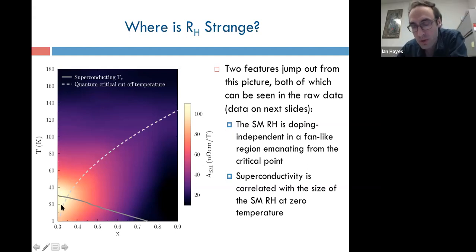That could well be true. It's a little difficult for me to answer with the high fields data because of the very limited field range available at optimal doping. I'll show you the raw data in just a little bit. When I do the fits and try to estimate how large the strange metal RH actually is, it does top out at around 10 to 15 Kelvin or something. Okay. So that is potentially consistent with that, if you have some cutoff of about a few Kelvin in this sample.